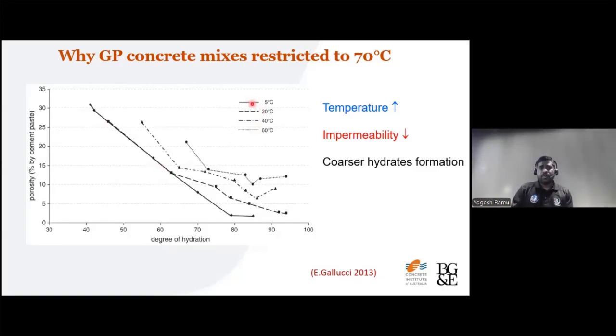If you can see, from 5 degrees Celsius to 60 degrees Celsius curing temperature, the porosity keeps on reducing as the degree of hydration is getting higher. But for the 60 degrees cured samples, even after the degree of hydration is beyond 90, the porosity remains roughly 10 to 15%, which justifies why we need a lot of SCMs in the system. So for a concrete with a similar heat profile, the pore refinement is much better, and the porosity can be very well reduced by using SCM.